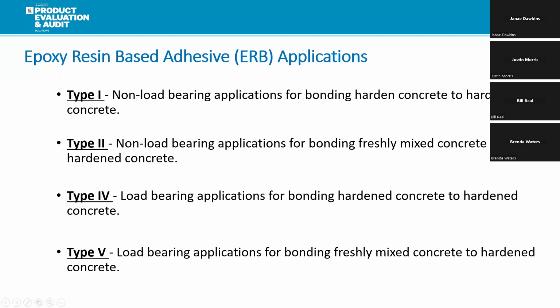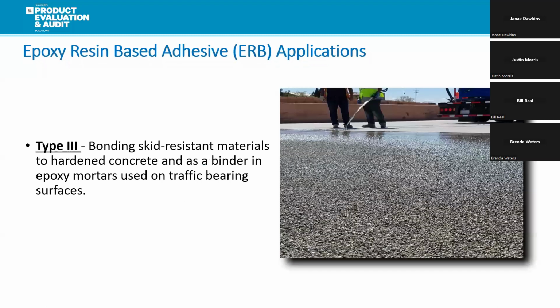So getting a little bit more into the definitions of the epoxies according to AASHTO and ASTM, you have your type 1, which is a non-load bearing application for concrete, hardened to hardened concrete. The type 4 would be a load bearing application of that similar usage, hardened to hardened concrete. Then you have your type 2s, which are non-load bearing applications of fresh concrete to hardened. And then your type 5 would be a load bearing instance of that exact same scenario. Also, type 1 and 4 can also be used to adhere other materials to a concrete.